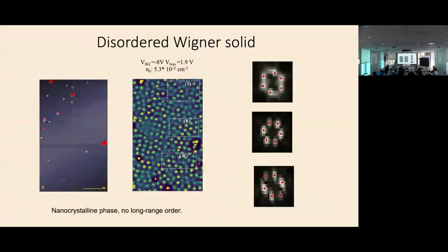So this is already a rather high density. If you think about gallium arsenide, usually the Wigner crystal is present at an electron density like 10^10 or even less. So this is actually several times 10^12. So it really benefits from the very strong Coulomb interactions because the dielectric constant is smaller, and also the effective mass is very large.